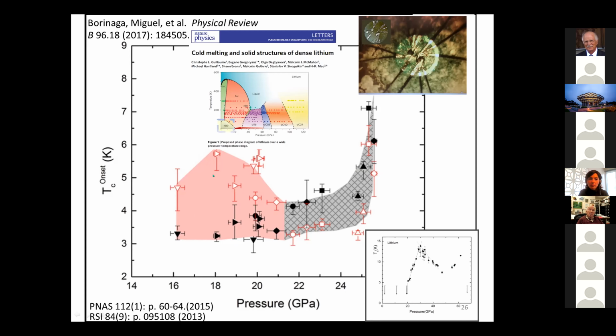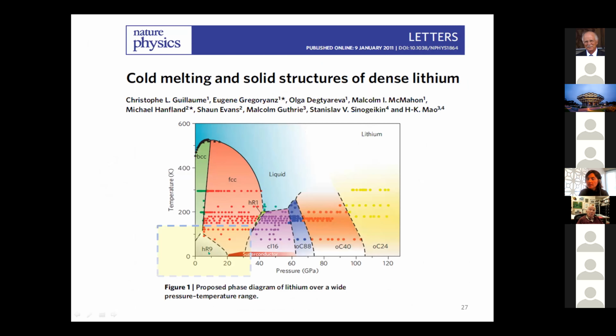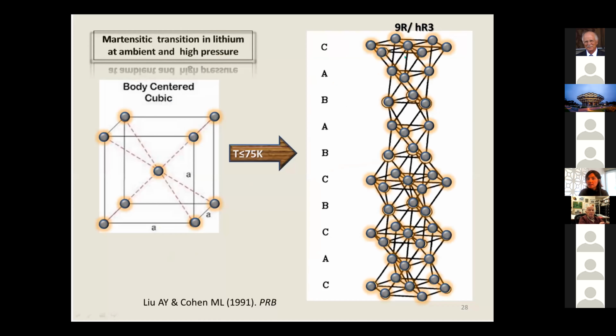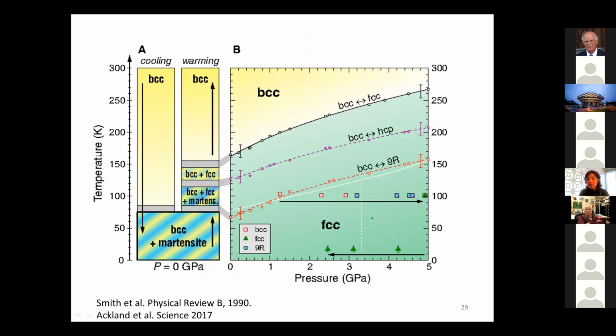The particular thing was this area of the low symmetry phase that was thought to be close to the superconductivity. We wanted to study it and see how the superconductivity can be related to this phase boundary. This is a Martensitic phase transition, and these boundaries had never really been studied. When you cool down lithium from BCC, even at ambient pressure, it goes to this stacking fault Martensitic phase. The interesting thing is that this phase is theoretically not predicted to be energetically favorable. Even the best theories suggest that when you cool down from BCC, you first have to land in FCC, and that is not the case. We always end up in this Martensite phase.